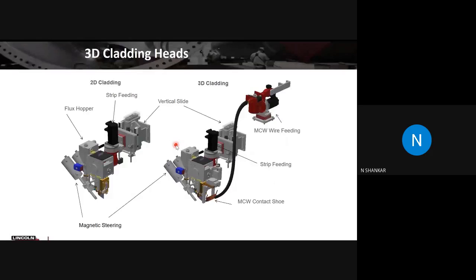And here is a photograph of the cladding head. This is the conventional 2D, or two-dimensional, cladding head, where you have a magnetic steering kit and you can feed the strips and then do the welding. Here is the additional wire feeder, the metal core wire feeder, which will feed the wire into the molten area to pick up energy from the overlay and then deposit the metal core wire there. So this is the 3D cladding one. In addition to the 2D cladding, we have a separate metal core feeder, and the rest of the things are taken care of by the power source and the electronic control part of the machine.